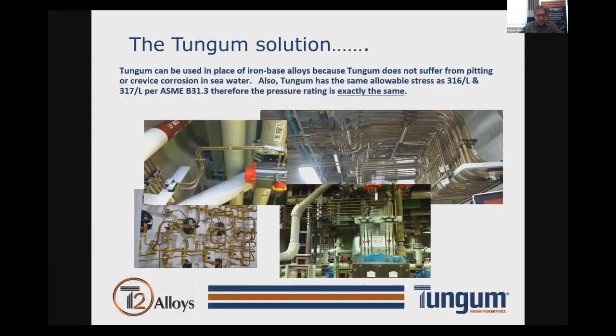Tungum, being a copper-based alloy, is very well suited for corrosion resistance in seawater applications, and ultimately does very well. One of the main benefits, of course, is the corrosion resistance. The other benefit is that because of the combination of alloying elements as well as the process involved in making the product, the strength of the material is increased. So according to ASME and ASTM calculations and allowable stresses, the strength of the material is almost exactly the same compared to 316 and 317.